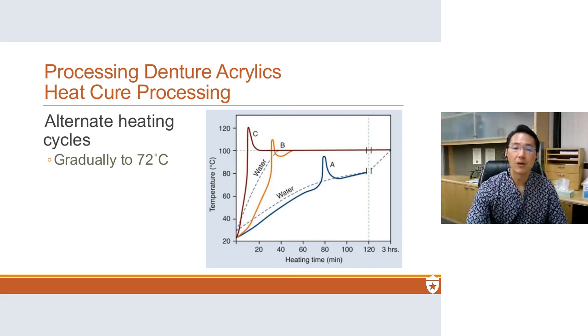So there are some alternate heating cycles. So this C is when you put it in boiling water, okay, and that's no good. And B is when you heat the water up too quickly, and you still get monomer boil here. Okay, but you can heat the water up really gradually and control it so that you don't get the boil. You just get that spike here, and you continue to heat it up to boiling point and further drive the reaction to completion. But there are other preferred heating cycles.